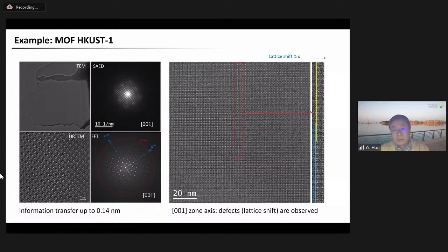And in a control experiment, we use FIB at conventional room temperature, and the MOF structure was completely destroyed. So we cannot get an image for that specimen. Okay, so this result confirmed that the stability of a MOF under the ion beam is greatly improved at cryogenic temperatures. So we propose that cryo-FIB is a promising method for preparing TEM specimen for MOFs and other sensitive materials.